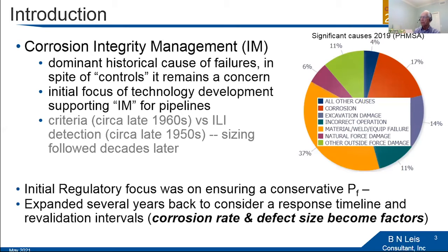So by way of background, we're in a conference involved with corrosion. Corrosion remains a major issue on pipeline systems, in spite of the fact that we've had controls in place for literally decades. Roughly 20% of the failures in the United States are caused by internal and external corrosion. Not surprisingly, corrosion initially was the major cause of failure, and it was the initial focus of technology development for integrity management for pipelines. The initial regulatory focus was on ensuring a conservative failure pressure, and recently that was extended to consider a response time and revalidation intervals, which open to concern corrosion rate and defect size.